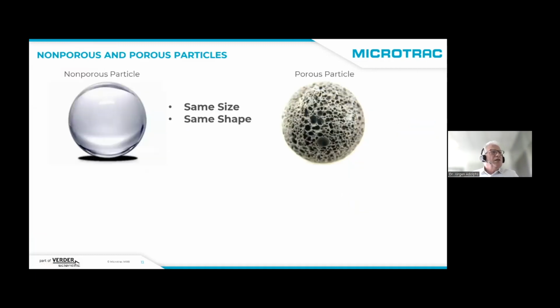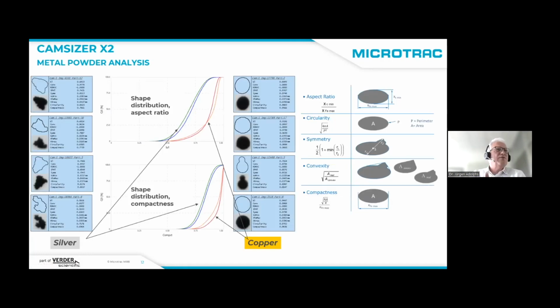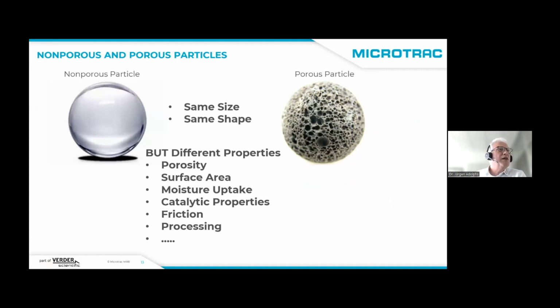So when we have particles with the same size and same shape, but they are non-porous on one hand, like on the left-hand side, or a porous particle like on the right-hand side, you will not see a difference in this kind of data, for example, for particle size analysis. But the behavior and the properties are very different, like the porosity, the surface area, moisture uptake, catalytic properties, friction, processing, and so on. And this is now the next step, that we will investigate and characterize porous particles.